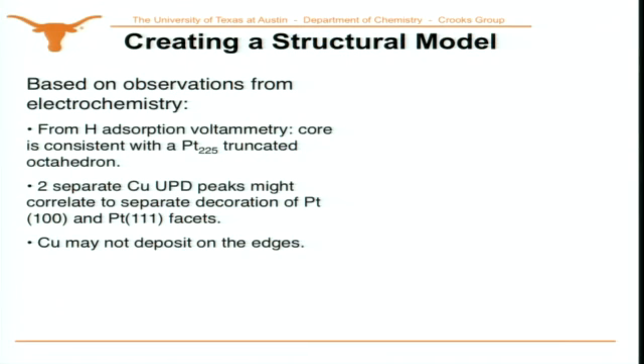So let me just recap the observation. The hydrogen adsorption data tell us that the core really is a 225 atom platinum particle. There are these 2 separate copper UPD sites, at least on this big 225 atom particle. And so we could imagine that some of that copper is being deposited on the 111 surface, some on the 100 surface. And we might imagine that copper might not deposit on the edges because those are very high energy sites, and it might not be the place where copper wants to be. And so this is the model we developed with our colleague Graeme Henkelman.